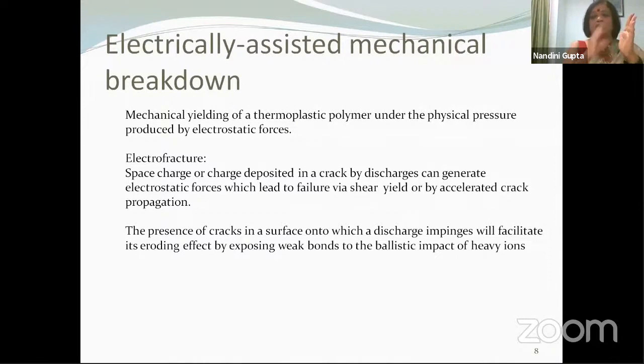You have positive charges and negative charges across, let's say, a thin film. And these positive and negative charges attract each other. So there are compressive forces. And these compressive forces can cause the material to grow thinner. And when the material grows thinner under a constant applied voltage, the electric field increases in the material, because E equals V by d, so as d decreases with V remaining constant, the electric field increases. When the electric field increases, it can lead to breakdown.